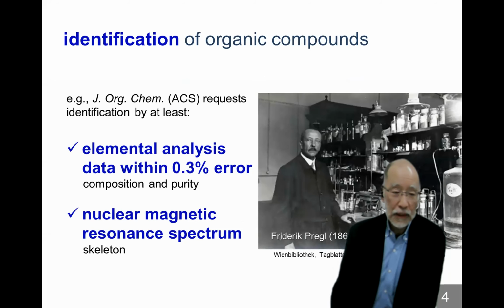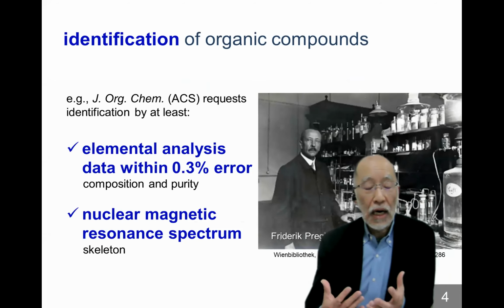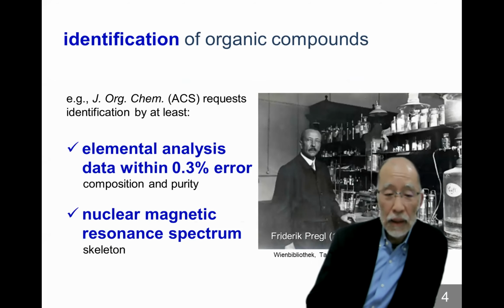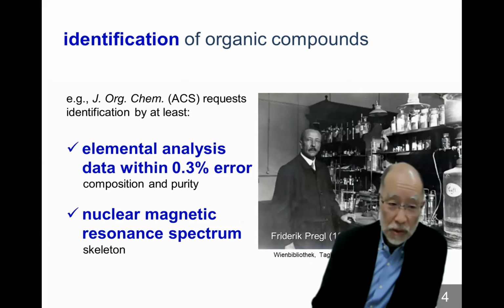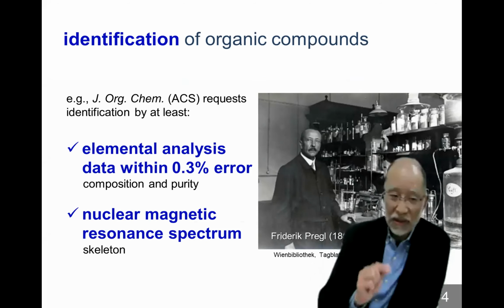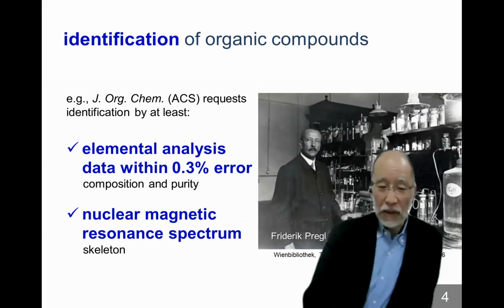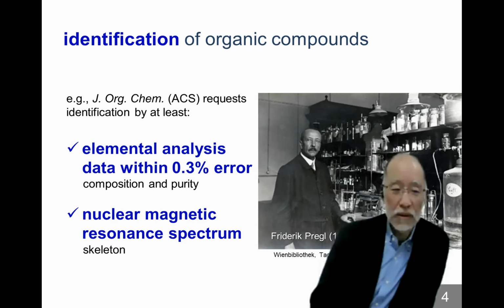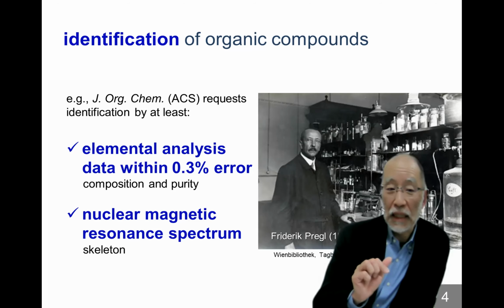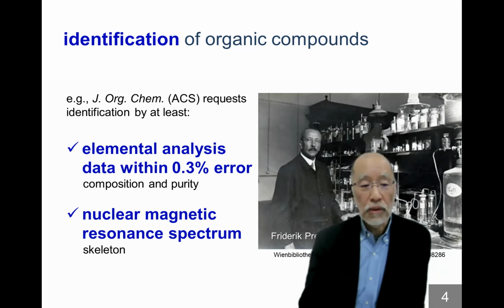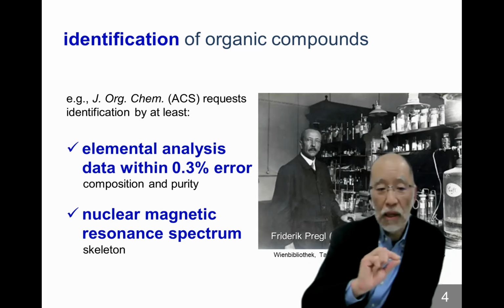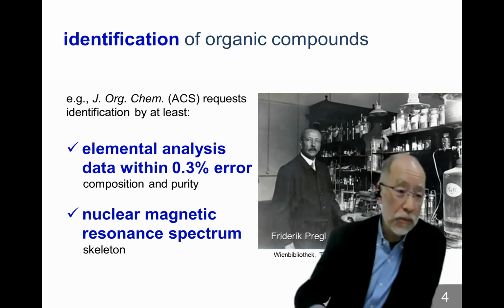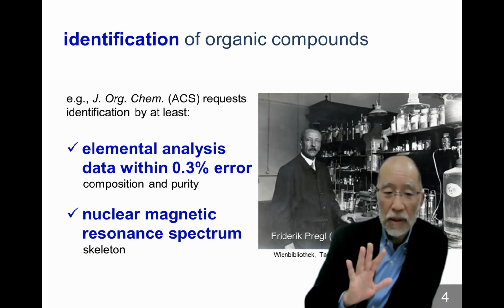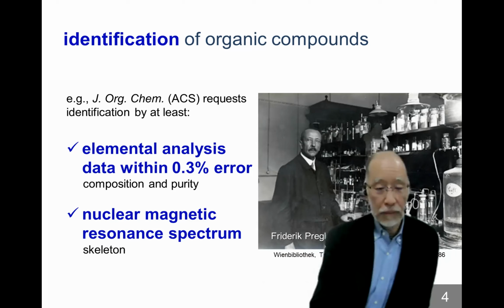For example, the Journal of Organic Chemistry published by American Chemical Society requested the authors identification by at least elemental analysis data within 0.3% error. That is very, very severe restriction. If you have experience of organic synthesis, the elemental analysis data within 0.3% error is very, very tough, challenging. And the nuclear magnetic resonance spectrum, this shows the skeleton. That is how the carbon atoms are interconnected. And by using those data, it is possible to identify.